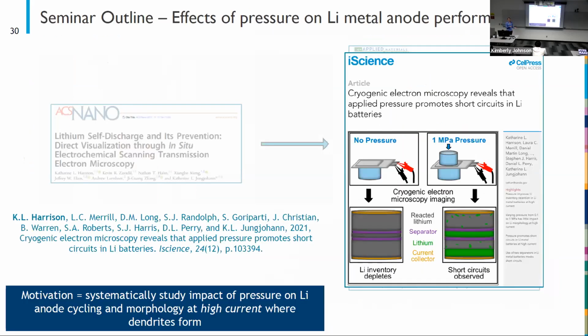So everything I showed you in that last pressure study, that experimental pressure study, was at low current density. Now we wanted to repeat that study at high current density where we actually expect dendrites to form. And we wanted to see whether pressure would stop the dendrites by just pushing on them, or whether we would see these transport problems arise and we'd make the dendrites worse.